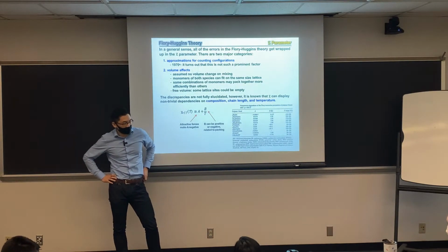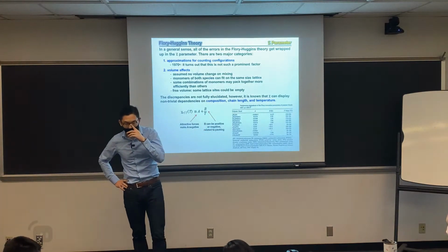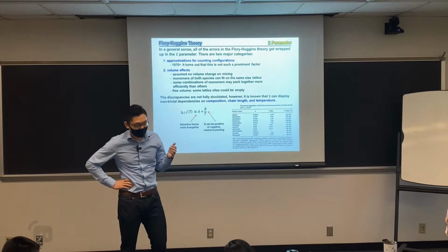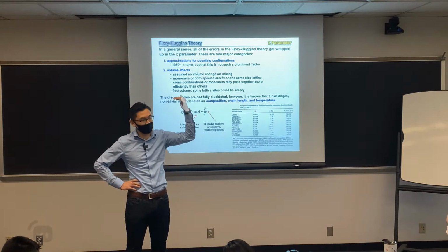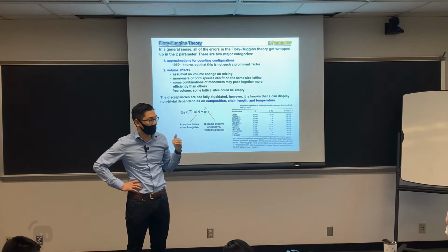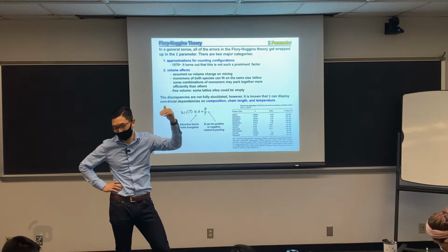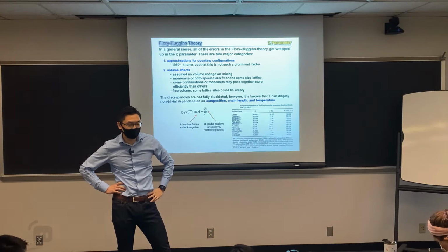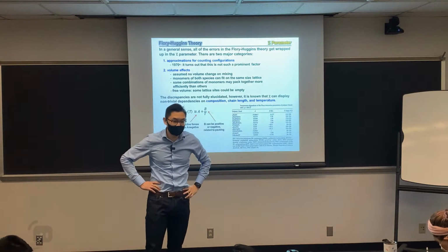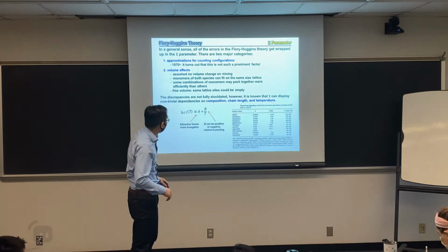There is a significance in the sign of B that we will talk about later, as it pertains more to phase diagrams, where if your temperature goes up, your chi goes up. One effect could be that at low temperature your polymer is mixed, but at high temperature your chi increases and it phase separates. So we could have LCST behavior, lower critical solution temperature phase behavior, which we will describe in more detail.